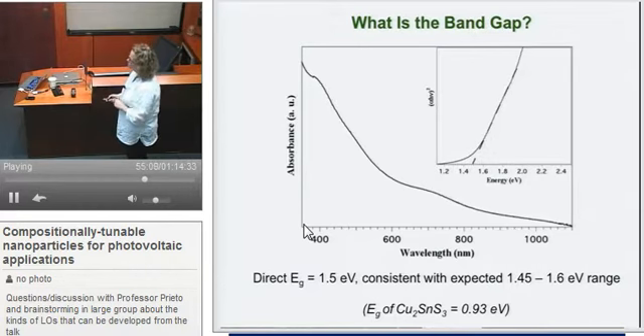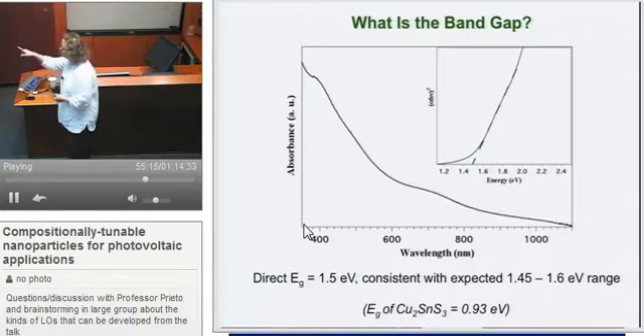The band gap we get here is about 1.5 eV, which is consistent with what's predicted for the bulk. The band gap of one of the impurity phases I showed you before, just as comparison, is about 0.9 eV, so again, a lot smaller. We have intentionally made mixtures of different combinations to get the right overall stoichiometry, and the absorption is really messy, so at least we can do that as a control.